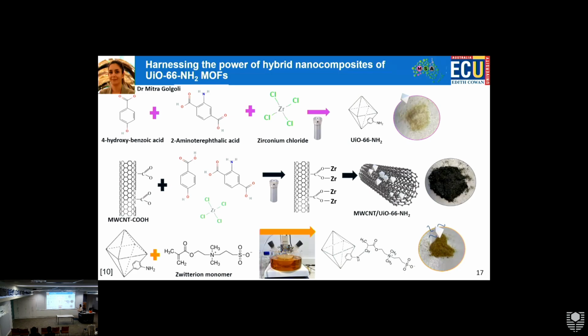So she used this NH2 to functionalize UiO66 because NH2 is the same functional group as in the MPD, m-phenylenediamine, that we used for interfacial polymerization of the selective layer. So it can easily chemically interact with the trimesoyl chloride, the other monomer that was in the organic phase. As you remember, we had an organic phase monomer and an aqueous phase monomer that were in touch and do a very thin layer formation on the surface of polysulfone.